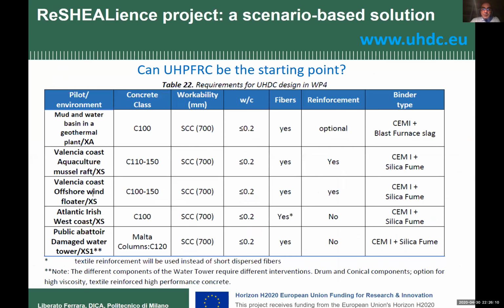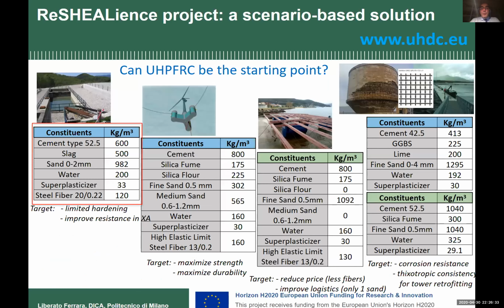So we worked with self-compacting materials and also with textile thixotropic materials. We did not use the same material everywhere, not only because the components available differed between countries, but also because the requirements were different. So our key idea is that you do not have a unique UHPC or UHDC material, but rather a solution-based, scenario-based material. We will focus next on the material framed in red here.